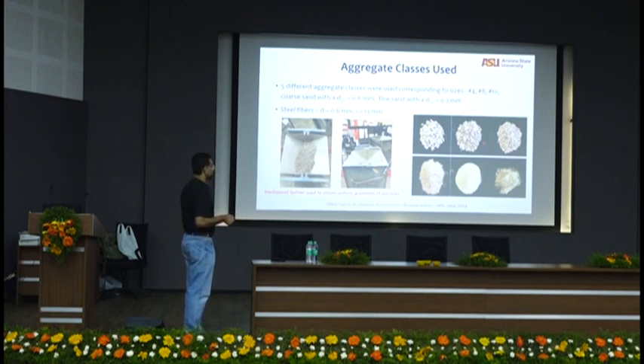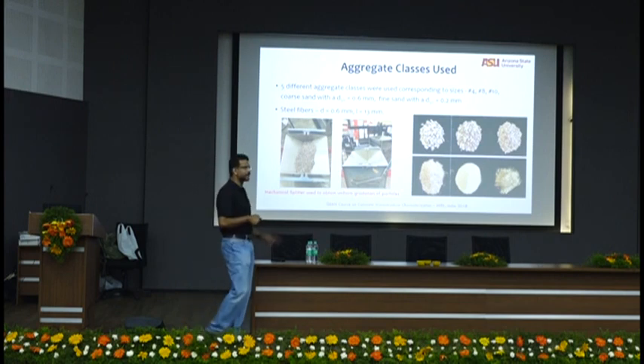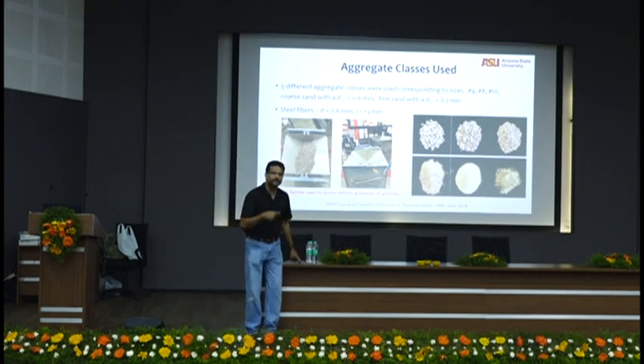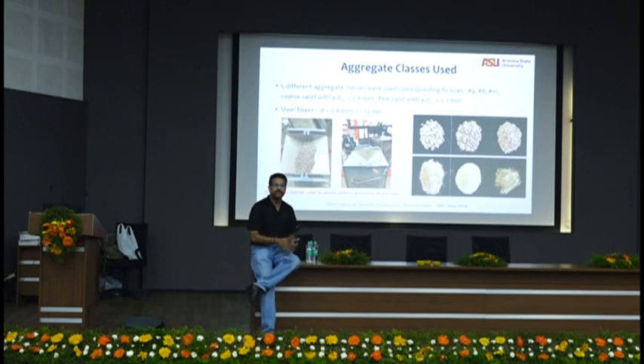And these are the aggregates, and we had to wash and clean so that the aggregates are really clean. Remember, every little impurity, every little defective spot is going to cost you when you're looking at very high strength concrete. When you look at 150 megapascal, it becomes tougher and tougher. You can get to 80, 90 without too much of a problem. Once you get beyond that, every single MPa is painful. Every little increment, you have to be very, very careful.